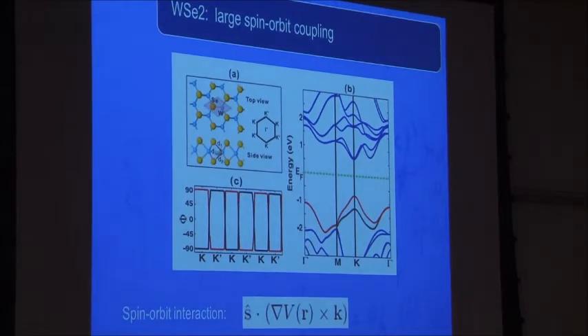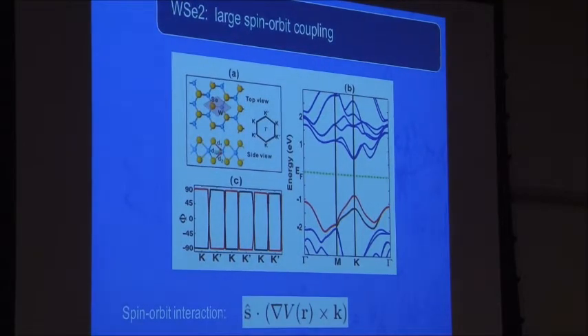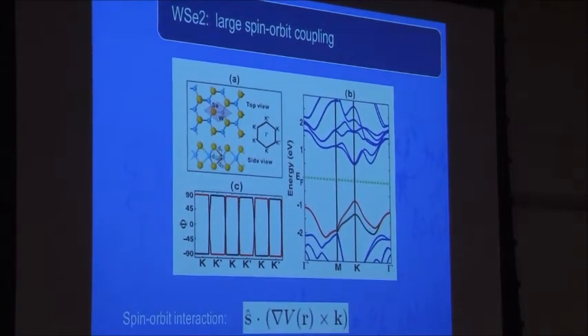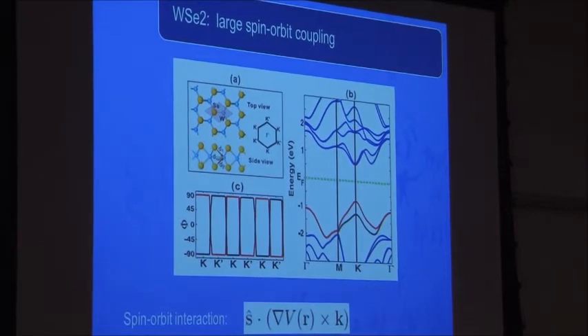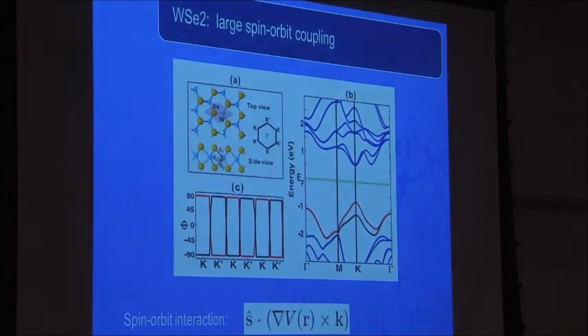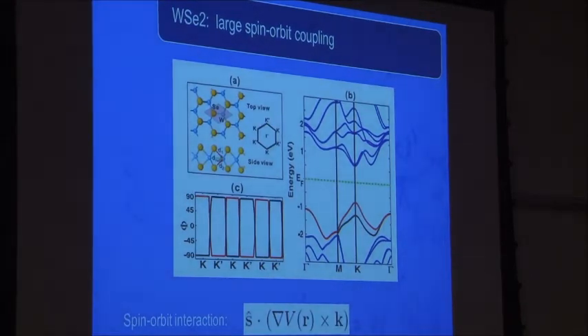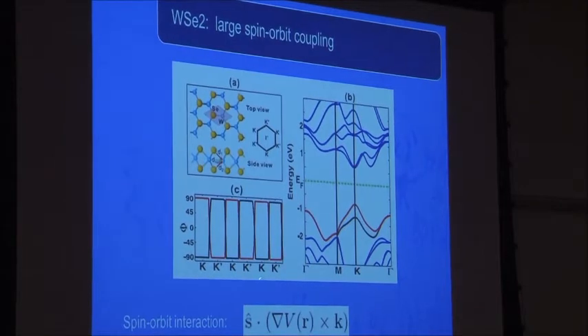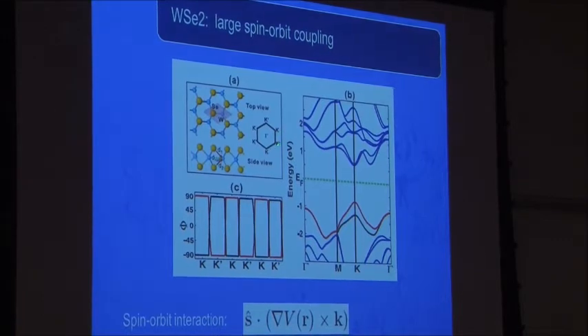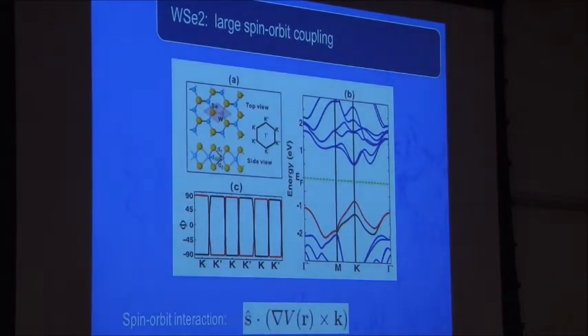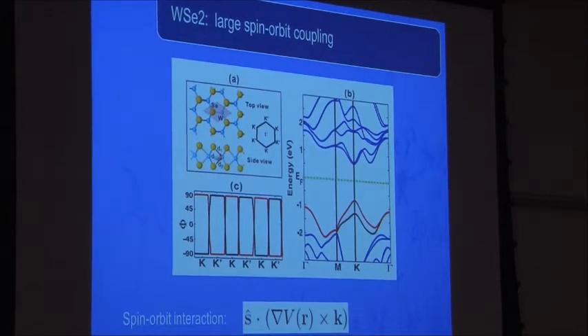Right? So when you have an effective magnetic field pointing in the z direction, it tends to orient your spins in the z direction. So basically your spin will be Zeeman-like, up and down. In this material, the spins will be at 90 degrees to the plane in a lot of places of the Brillouin zone, plus or minus 90 degrees. So they are either up or down spin, pointing like that. They are at the K and K prime places in the Brillouin zone. The spins at K are all spin up, at K prime all spin down.